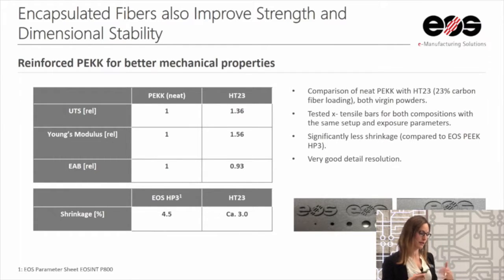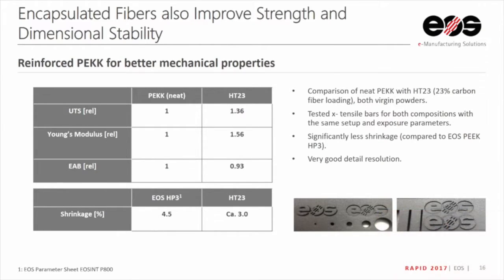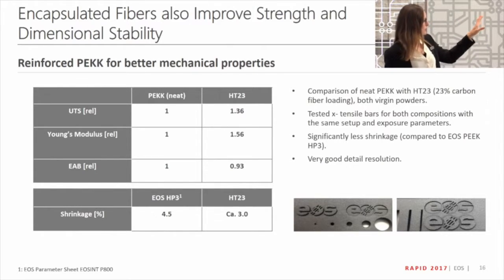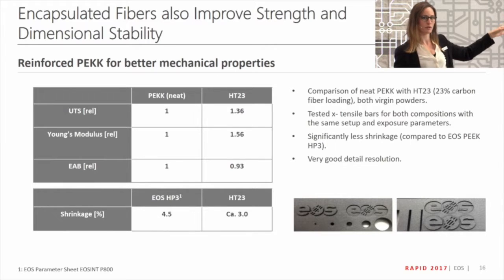And that adding or the encapsulation of carbon fibers not only helps with the isotropic behaviors, but also improves the strength and the dimensional stability or the shrinkage of the final parts. And I compare here the HT23, so the carbon fiber encapsulated polymer, with a neat PEKK, so a PEKK without any carbon fibers. And you can see the tensile strength and the modulus increase. The elongation break decreases a little. That's just because it becomes stiffer and then the elongation goes down.